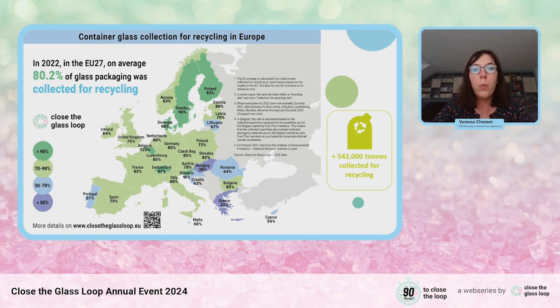As Close the Glass Loop, because we have our 90% collection target, of course, we try to keep track of the collection rate. But what we realize is that it's more and more difficult because member states have to report to the European Commission a real recycling figure. So it's quite difficult in some countries to have the collection rate. So I want you to be aware that some of the figures on the map are real recycling rates and not a collection for recycling rates. So the average that we have is probably a conservative estimate. So that's on the methodology.